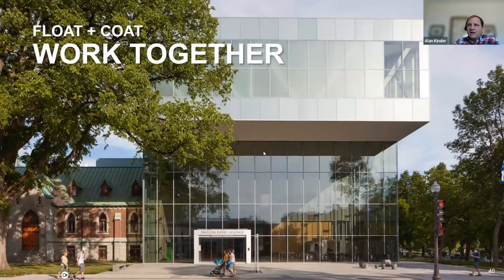And as we start to look at the other facade, the orientation of the building, the other dynamics that come into that built environment. So one of the things to look at here is we have a large box overhanging this glass facade. And due to the nature of the elevation of the sun, time of day, you're actually getting pretty significant shading of this glass facade. So where we have a lot more of that shading and the light's not penetrating deep in those interior spaces, we get a darker appearance to the glass. This is still 68% light transmission with only 11% outdoor reflectivity.